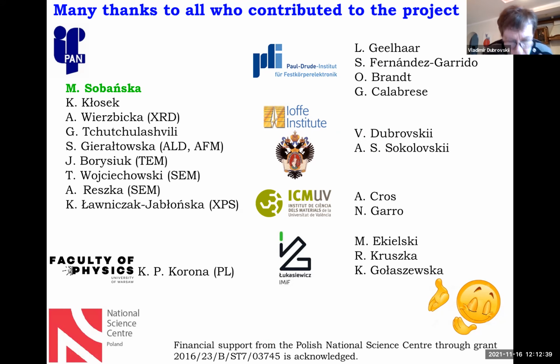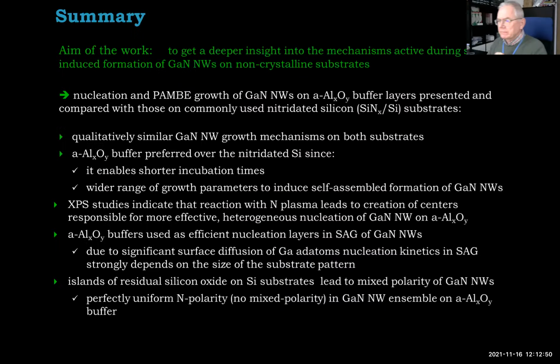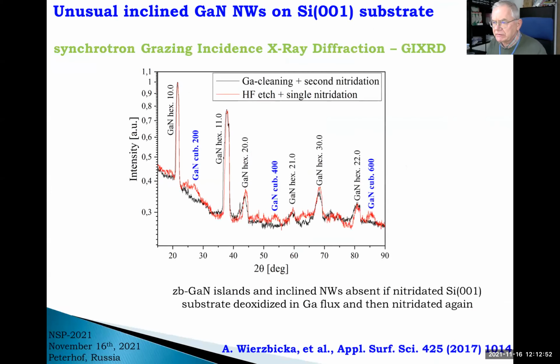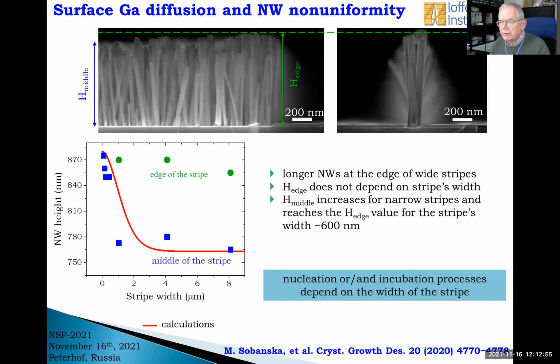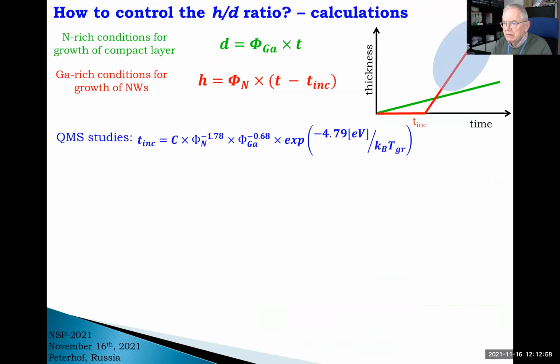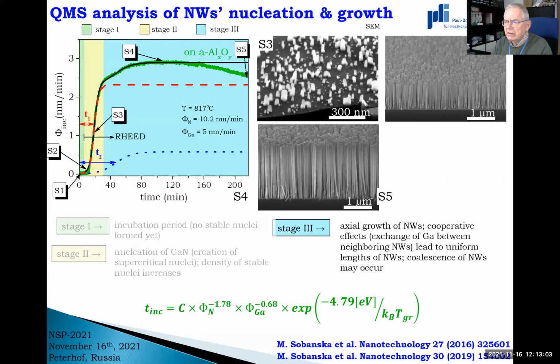My question is, can you actually observe coalescence of gallium nitride nanowires in your experiments? I mean, I showed you that we see this in situ actually. The black curve here is a model which does not include coalescence at all. In real life, we observe this decrease of QMS signal, and this is due to the coalescence.